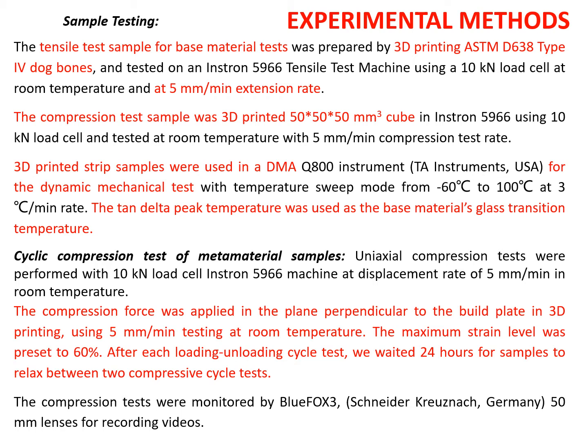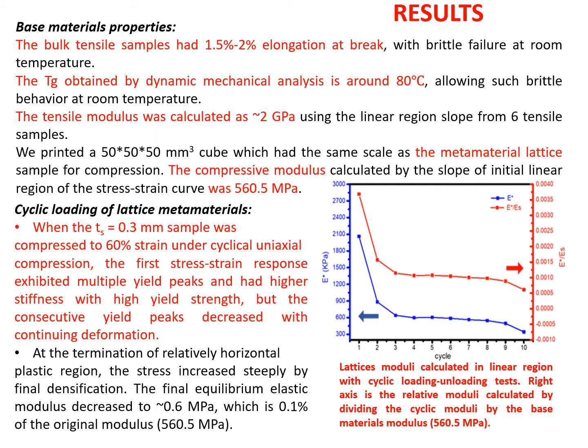We performed cyclic compression tests on the metamaterial lattices. The compression force was applied in the direction perpendicular to the build plate in 3D printing. Using 5 mm per minute testing at room temperature, we obtained maximum strain level up to 60%. After each loading-unloading cycle test, we waited 24 hours for samples to relax between two compressive cycle tests.